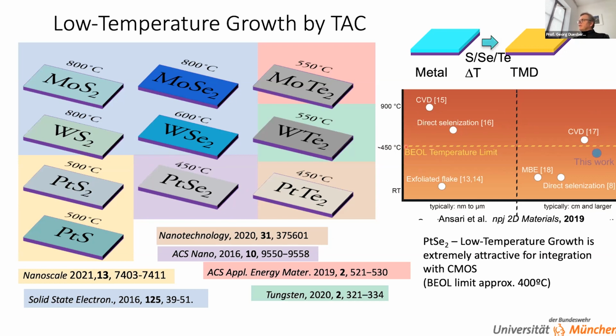And this is very important for silicon people because this is a so-called BEOL limit, which basically means silicon circuitry can survive below, some people say it's 400 or even 350, but roughly it's around this temperature. Also, aluminum leads can survive this temperature. So everything you can do below this temperature can be done on existing chips. So that makes this a very critical process temperature if you want to integrate it with silicon circuitry. So that was the first thing that raised a lot of attention to this material.